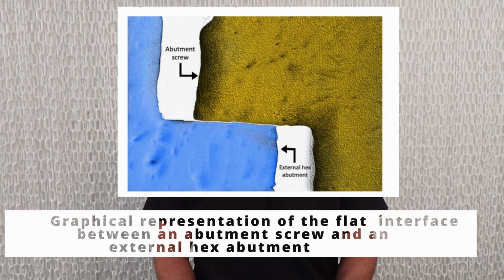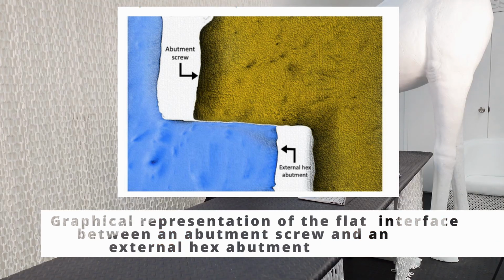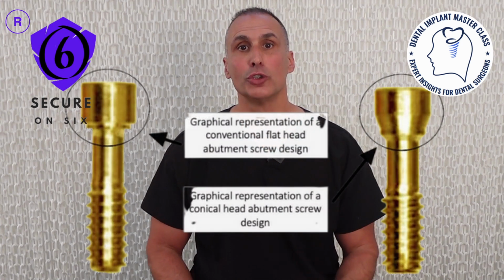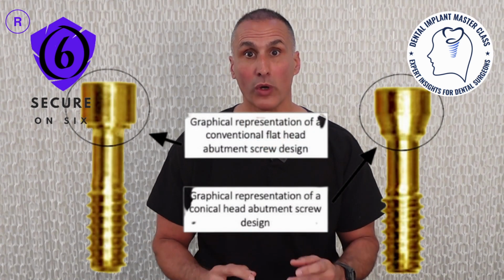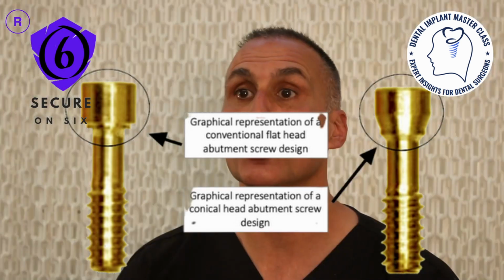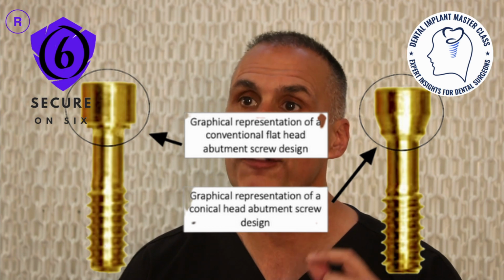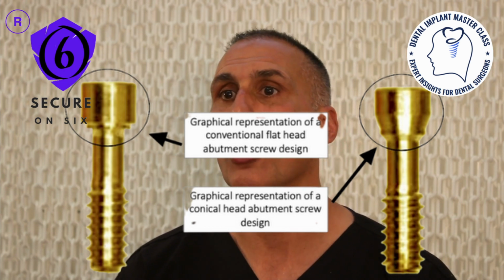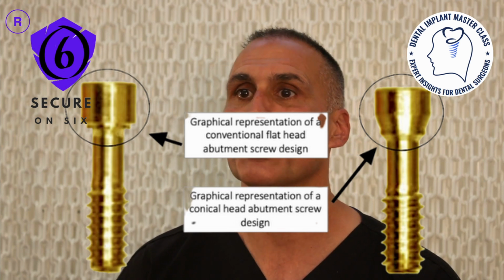Flat head screws, due to their reduced surface contact, exhibit significantly less frictional resistance when tightened compared to screws with bevels or tapers. This results in less input torque being lost due to heat and friction, allowing more torque to be transferred into the usable preload. Consequently, flat screw heads consistently offer higher preload levels within a given torque range compared to tapered or beveled screws, making them more stable, as demonstrated by Permiati in 2006.